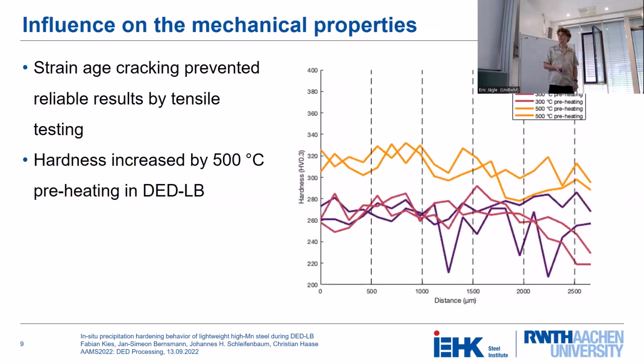And the influence on the mechanical properties is a bit difficult to determine, at least in tensile testing, again because of strong strain age cracking. But if we take a look at the hardness, so these are curves at different preheating temperatures, 0 and 300 degree preheating led to a mean hardness of about 270 Vickers hardness. And in the 500 degrees preheated sample, we see a strong increase in hardness. So it really did lead to a strengthening effect.